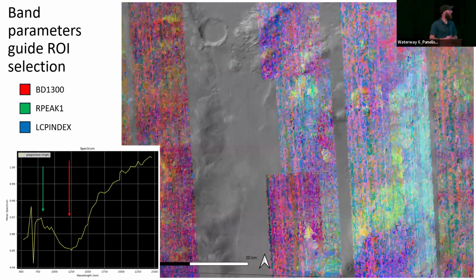So the way we went about doing this is we used CRISM mapping data. There's a really nice new data set that came out just last year, the MRDR-V4s. A big thank you to Frank Seelos for pushing those out and a lot of other folks at APL. And so we use this specific band parameter combination where we track the band depth at 1300 in the red channel, the reflectance peak at 1 micron in the green channel, and then the low calcium pyroxene index in the blue channel. The reason for the red channel ought to be obvious because we're looking for this broad absorption feature centered around 1250 or 1300 nanometers.